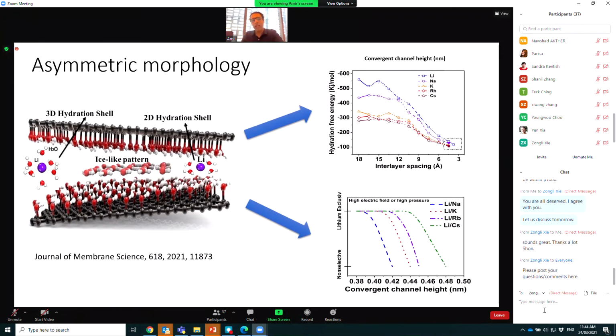What we found is that when you create this sort of conical or asymmetrical structure, the first thing that happens is you suppress the 3D hydration shell of the ions, and it becomes 2D hydration. So at the beginning of the asymmetric nanochannel, the ion has a 3D hydration shell. As it moves along the length of the nanochannel, it becomes 2D. The other thing, as I said, is the ice-like pattern that forms within the nanochannel because of confinement. You want to have the ice-like structure because of selectivity. You also don't want to have the ice-like structure because it compromises your permeability. So you have to play around with that.